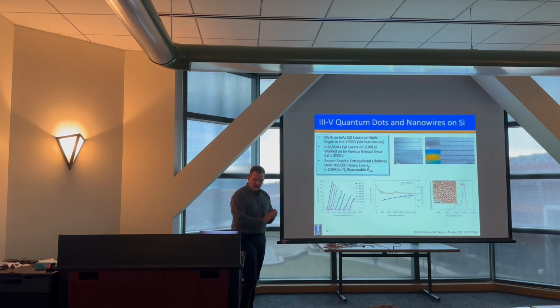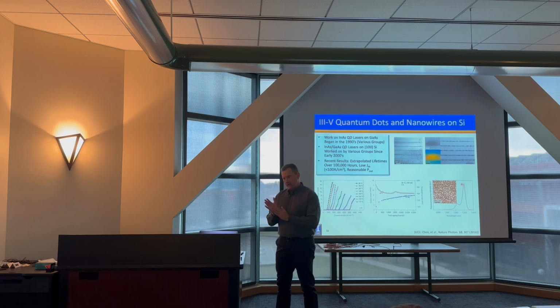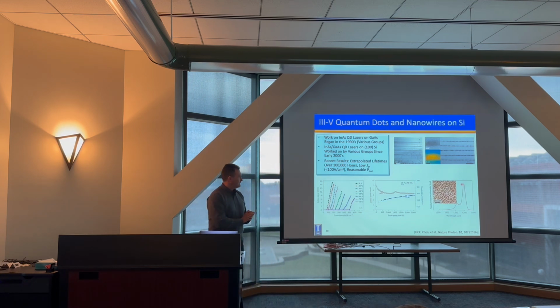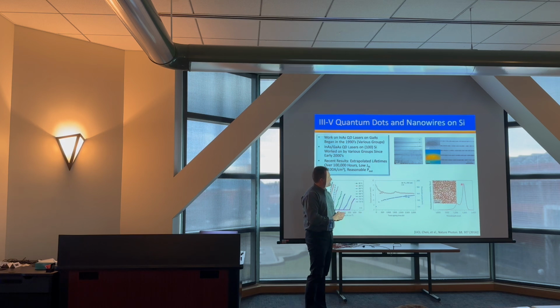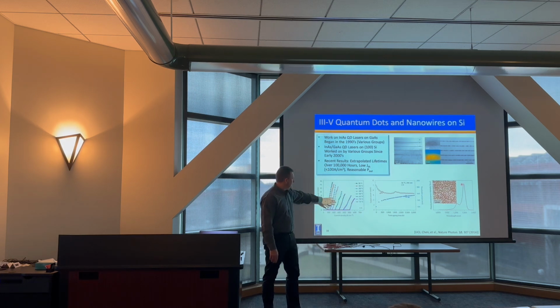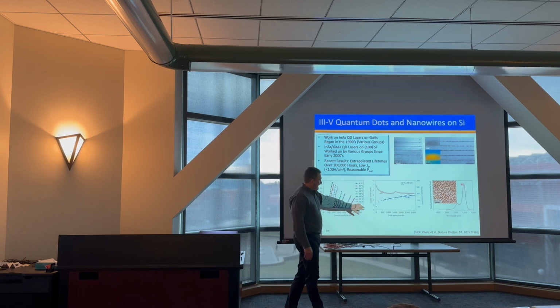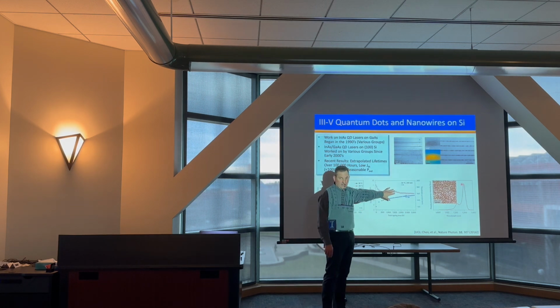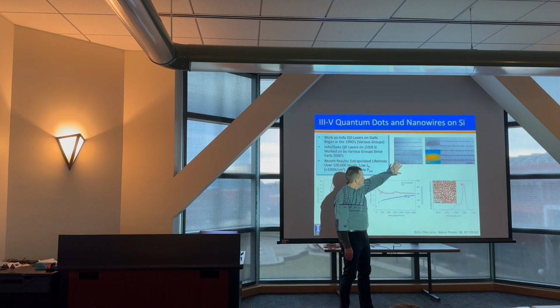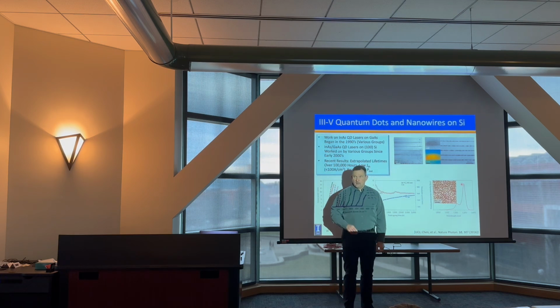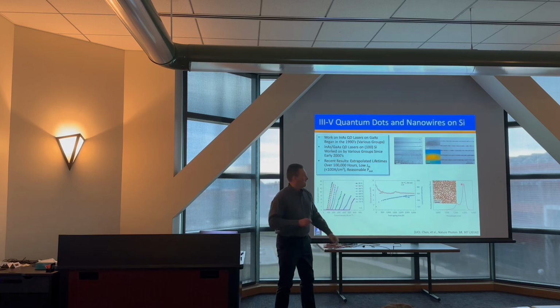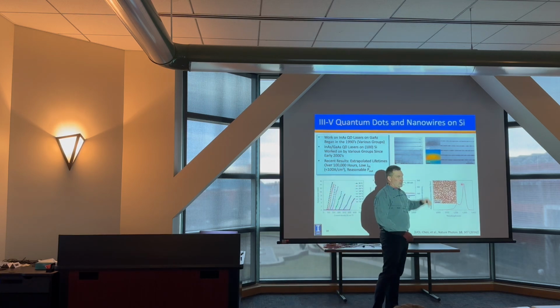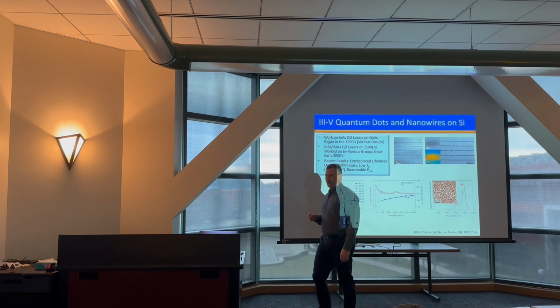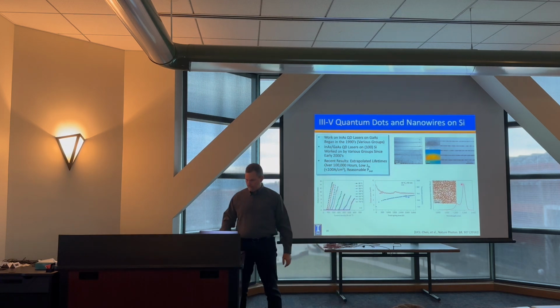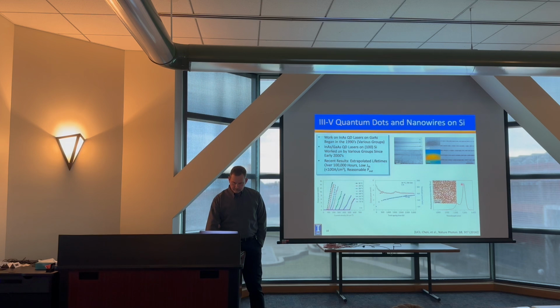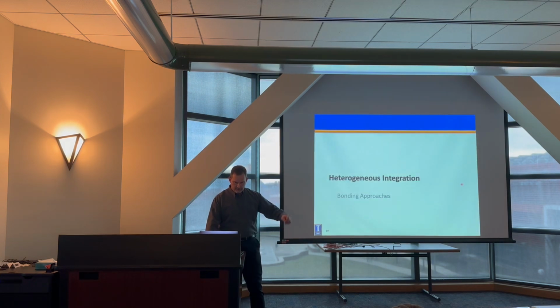And I mentioned the indium arsenide quantum dot work, and this is again another interesting demonstration where they were able to make, in this case, not bad lasers with reliability that was reasonable, using structures that had defects, but because of the quantum dot, if the defect intercepted the active region, it would not cause the same kind of lethal damage that you'd see if you had a quantum well device. Okay. That's a little bit on direct growth methods.